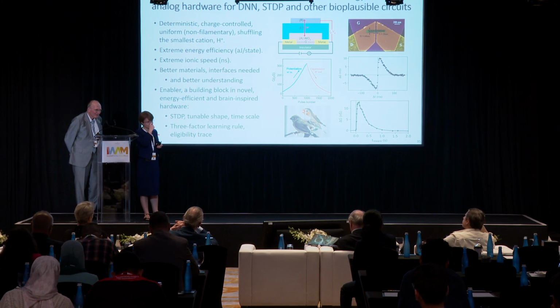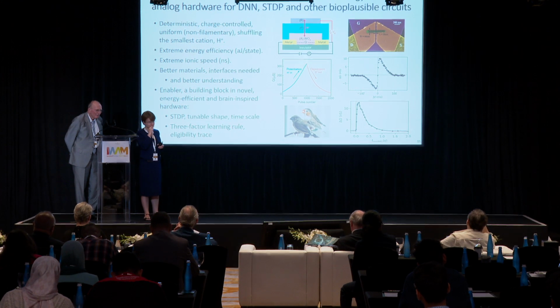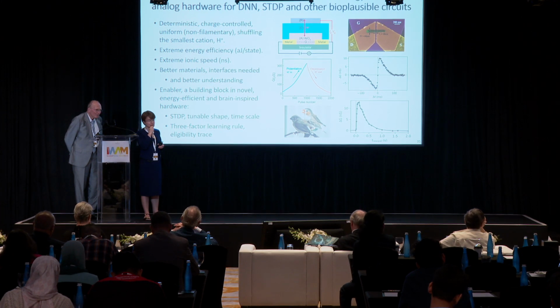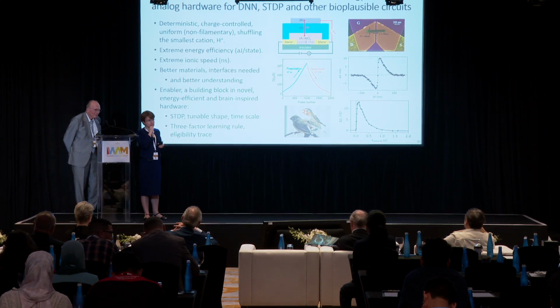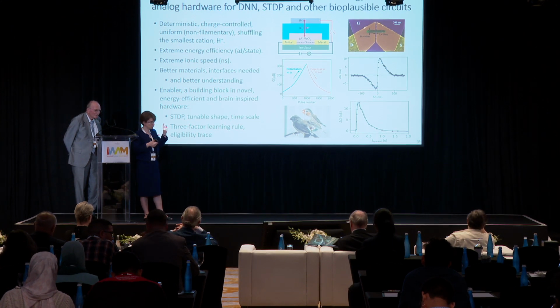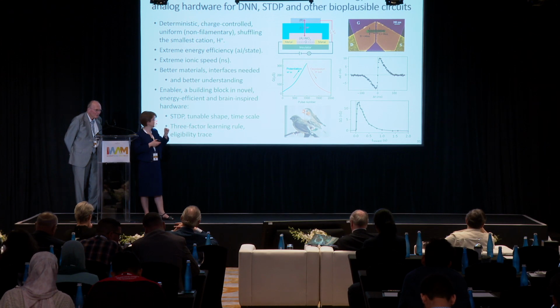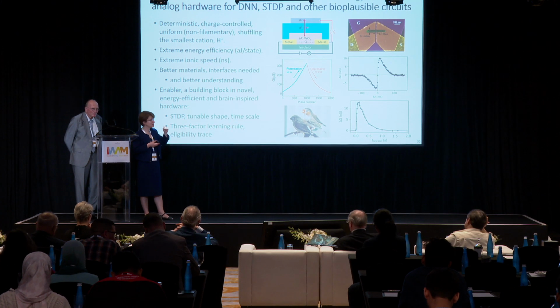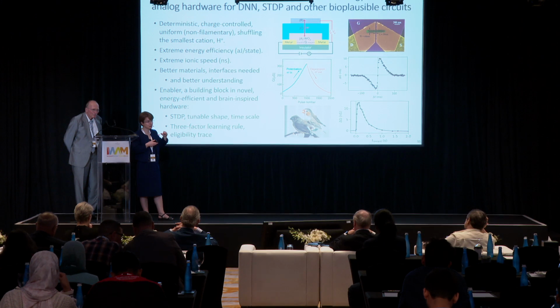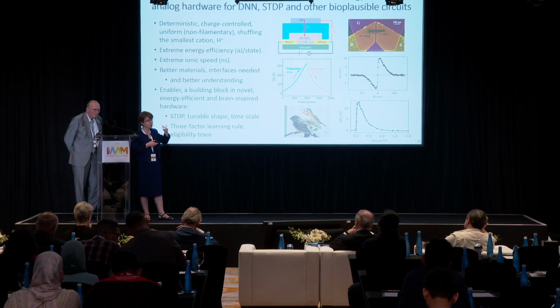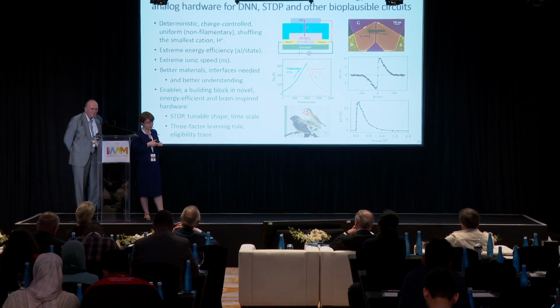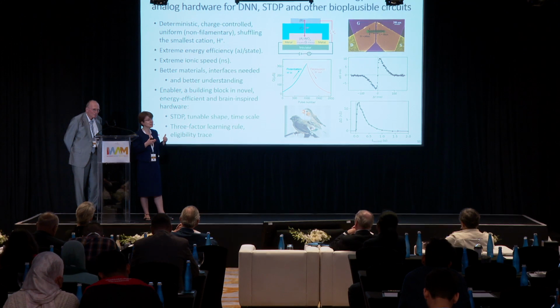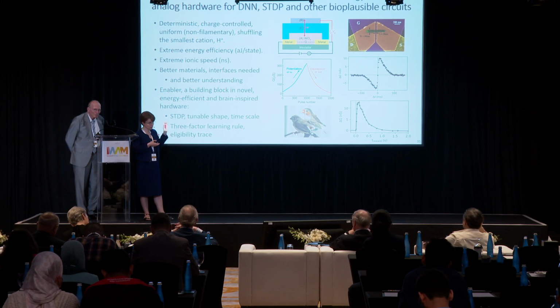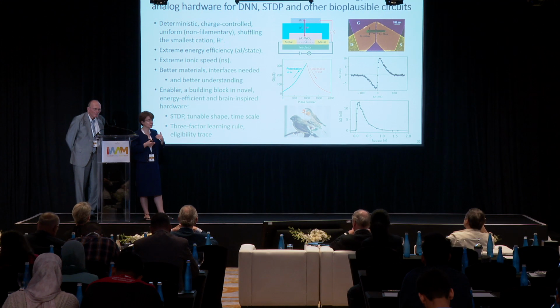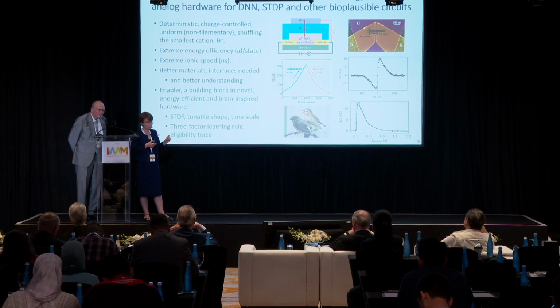So is the extreme sensitivity of the conductivity of the tungsten oxide to the hydrogen concentration really a good thing? Because it means that you may have more variability from device to device, because it's going to be hard to exactly control the amount of protons, right? You would think so, but because the conductivity modulation is through this in-gap state, as I mentioned. If the in-gap state position stayed the same, it should have been linear, but it actually moves up with increasing proton concentration. And that stronger than linear sensitivity comes from the moving of that in-gap state. And because it's intercalation, it's not microstructure that's involved in that concentration regime, so it's actually much more repeatable than if it were some extended defect dominated. Okay. So actually it's a good thing, because you need that extreme sensitivity so you can work with small proton currents or small gate currents.